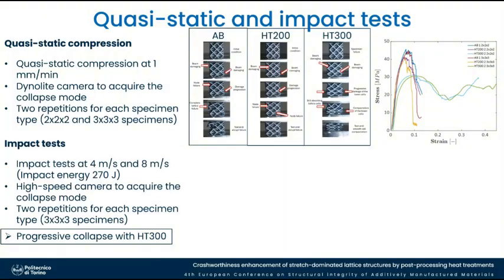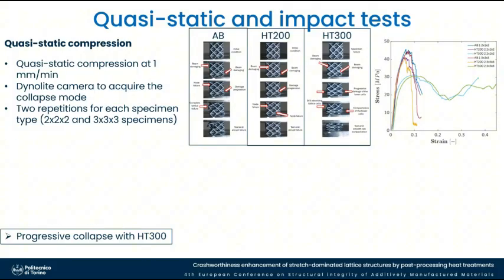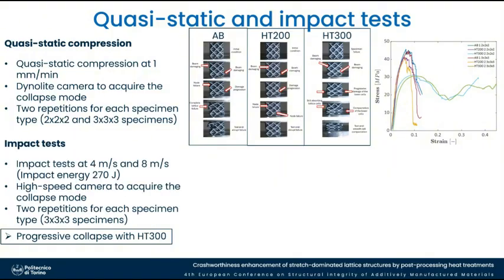And also here we observe, I'm reporting the results in terms of stress and strains, because I'm comparing both the 3x3 and 2x2 specimens. And here we don't see any significant difference between the two. That means that there is no size effect at this scale, at least.